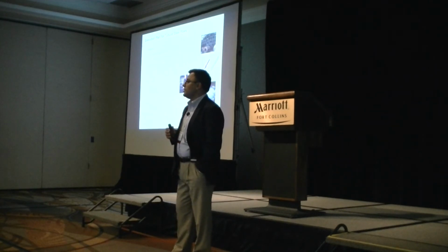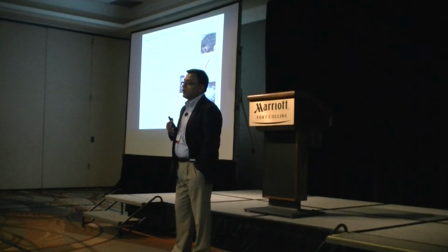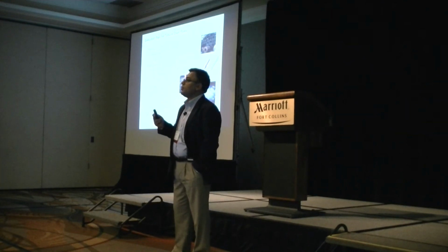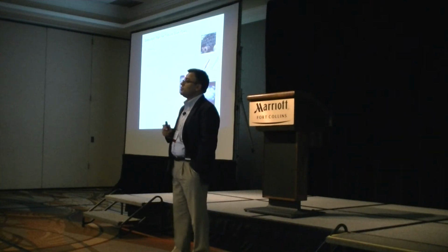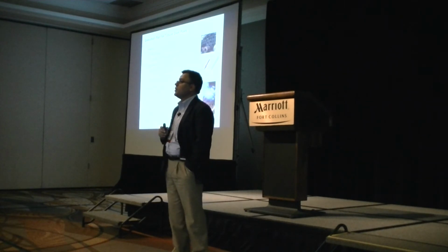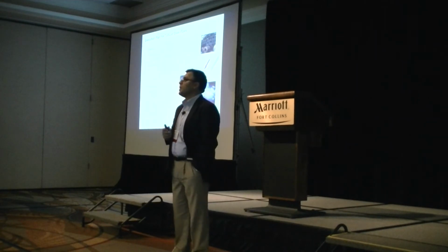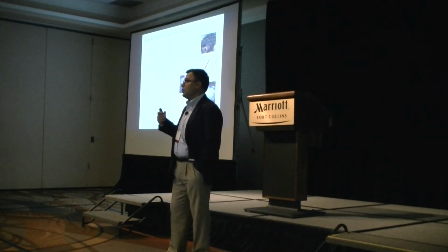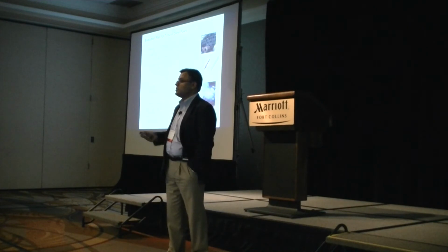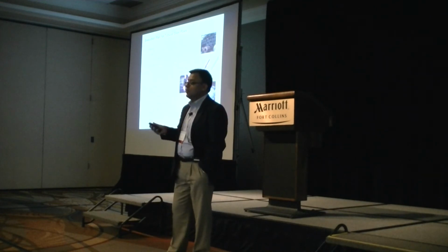Another thing we always face challenges with is that if you have an ASTM coil material, you make sure that after decoiling, you test it again. Sometimes you may have a variation of mechanical property if you test it after decoiling. So a lot of times the suppliers get oversight and don't pay attention to that. Just make sure that you do a test MTR after decoiling.